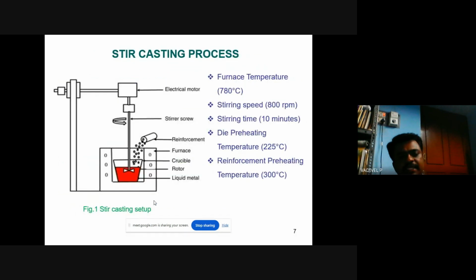This is the schematic diagram of a stir casting setup. Here we are using an electrical motor with a stirrer screw, the reinforcement, furnace, crucible, rotor, and the liquid metal. The furnace temperature is maintained at an average of 780 degrees Celsius, the stirring speed is maintained at 800 rpm, and the stirring time is a maximum of 10 minutes. The die is preheated to a temperature of 225 degrees Celsius, and the reinforcement preheating temperature is 300 degrees Celsius.